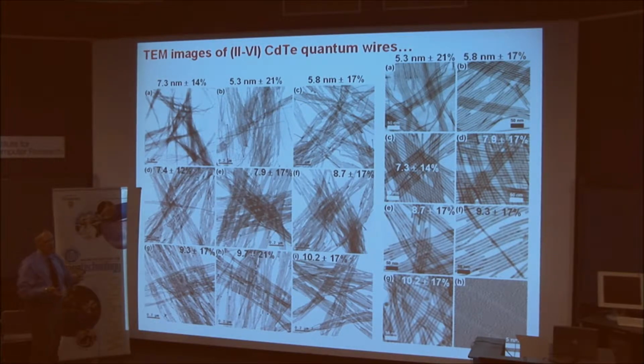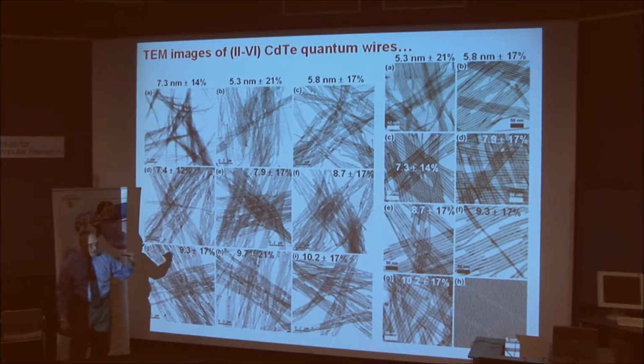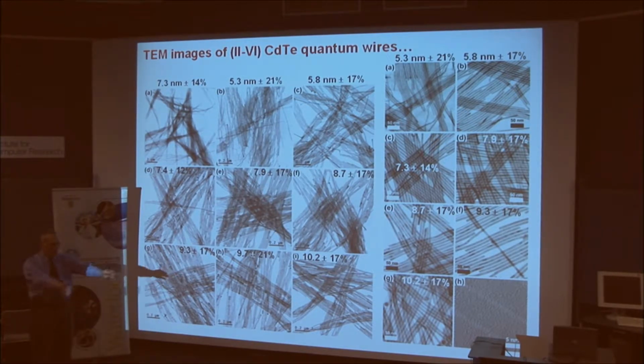So you can make a nice dispersion of wires in toluene, for example. It'll look just like a colored solution or a colored suspension. If you put that vial on your desk and go off to lunch and come back, the wires will already have begun to bundle because of these favorable interactions. And when the bundles get large enough, they start to precipitate.